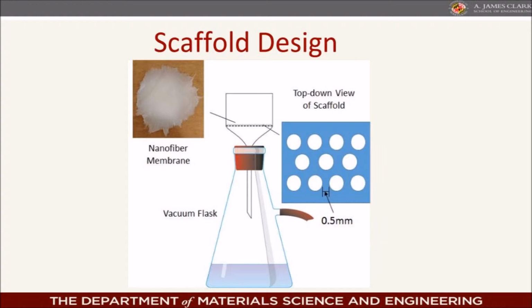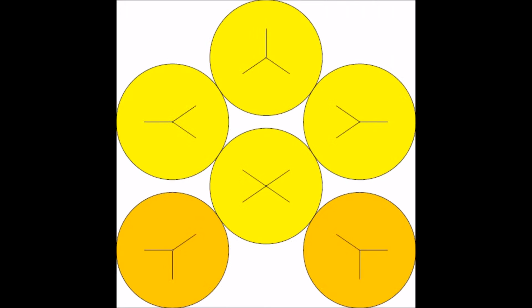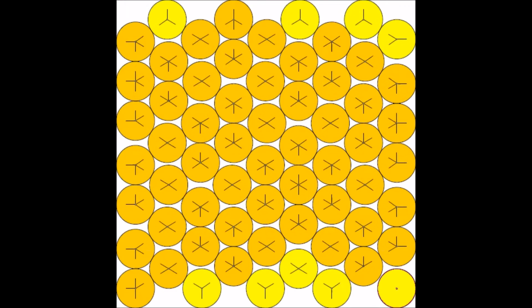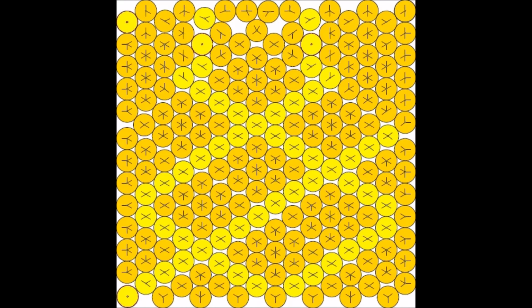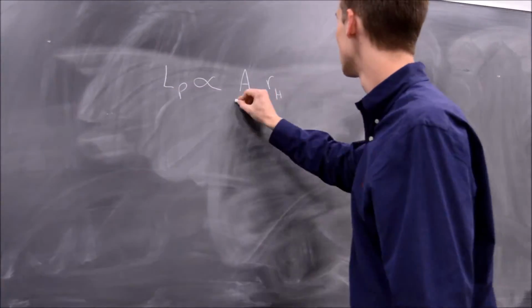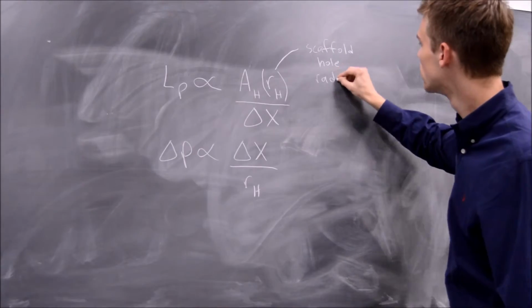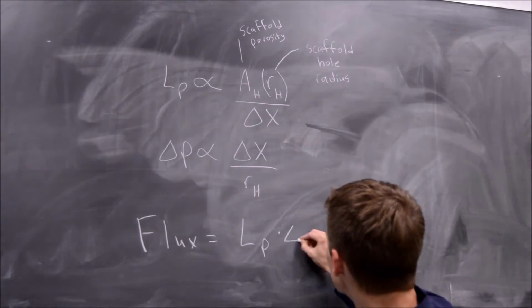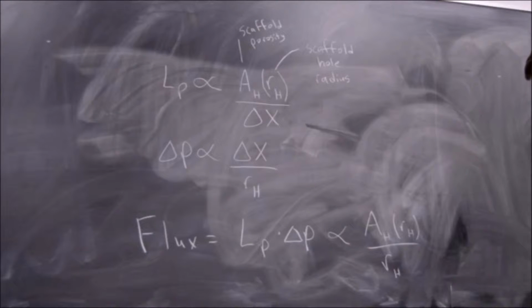To prevent confusion with the pores of the filter membrane itself, the pores of the scaffold will simply be referred to as holes. We found that as the size of the scaffold holes decreases, the porosity of the structure increases. However, because there must be some border between the holes of the scaffold, eventually the scaffold becomes dominated by this border. This results in a sharp decrease in scaffold porosity. The product of the two values of pressure and water permeability gives the flux of the filter, our primary performance metric. This equation suggests that the flux of our supported filter would be directly proportional to the porosity of the scaffold divided by the radius of the scaffold's hole.